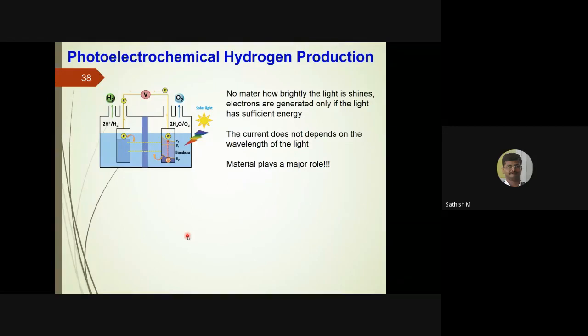If, for example, your hydrogen evolution rate is very high, but the oxygen evolution or this oxidation reaction in the other side is very small. For example, this is a compartmentalized cell. This H plus is reduced to hydrogen, and then here you have the photocatalyst or photoresponsive material. When you shine light, the electron hole pair will be produced. The electron moves through the external circuit, and then here it will produce hydrogen. So the hydrogen will be evolved here.